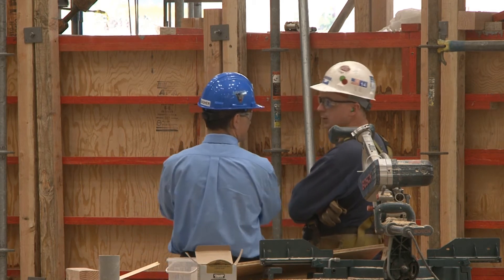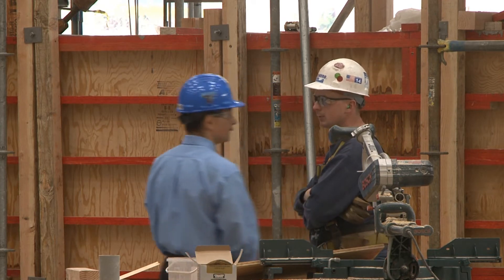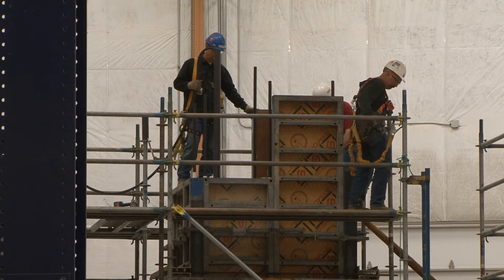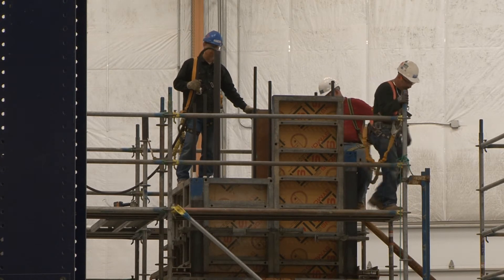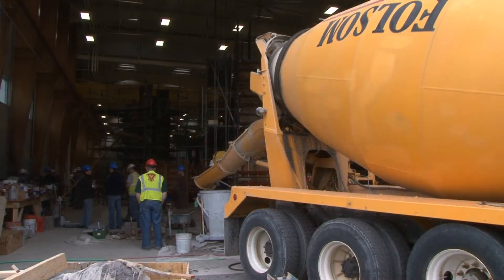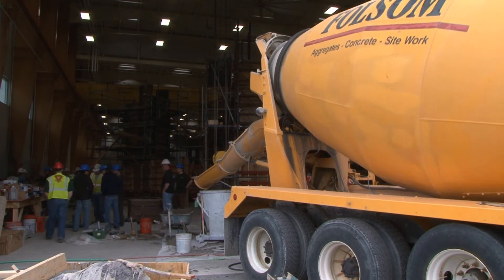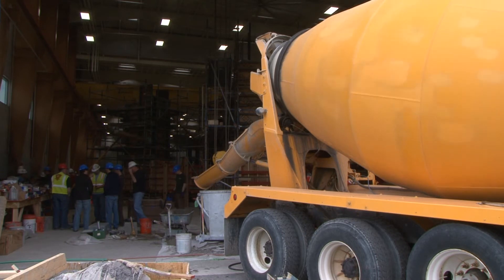The unit was fabricated completely in the lab right behind the curtain by the Cianbro team and UMaine team working side by side. What you'll see behind is just the hull — the tower and turbine aren't on top because they won't fit in the building. The hull is made out of very unique concrete that weighs only 105 pounds per cubic foot and has over 8,000 pounds per square inch capacity — a very lightweight concrete requiring a special mixer designed for this project.